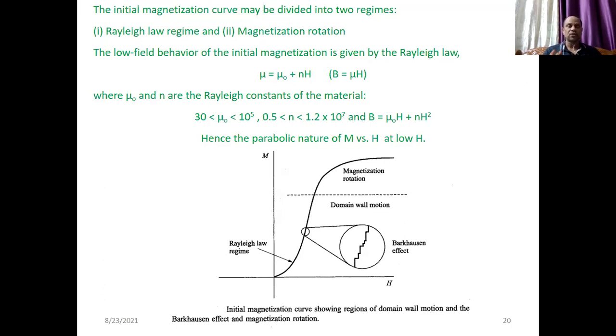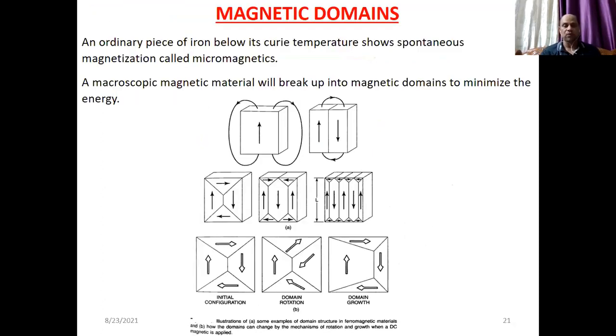From this simple understanding, if you have a cubic crystal, there will be 4 easy axes, and you cannot fix one axis. If you fix your magnetic field in the X direction, then Y, Z, and the diagonal are hard to the field. So each and every material will have anisotropy. Anisotropy comes when you apply the magnetic field, and it will never let the material saturate; it will keep increasing the magnetic moment. When you remove the field, that anisotropy energy is stored inside the material as your hysteresis, and that gives you the property. Whatever I told you: when you apply a field, the domain wall moves and melts, and then your anisotropy comes into the picture.